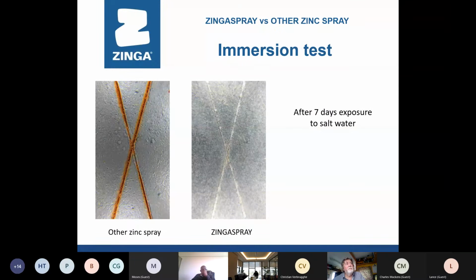Here's an immersion test to show you 1 form of zinc versus Zinga. The panels are sprayed, the zinc's allowed to get hard, and then they cut it through with a very sharp blade. They cut it through into the surface of the steel, and then they expose it to salt spray, salt fog mist. So the salt is spraying onto it 24 hours a day. You can see the zinc spray has immediately rusted inside the cuts. The Zinga is still perfect because the voltage is flowing into the steel, fully protecting it.